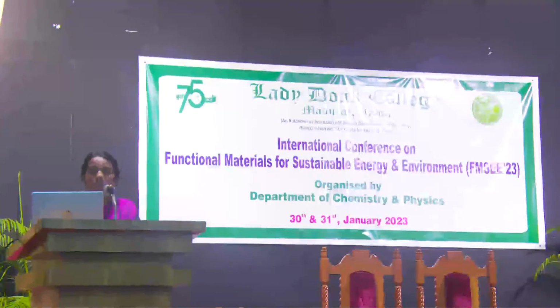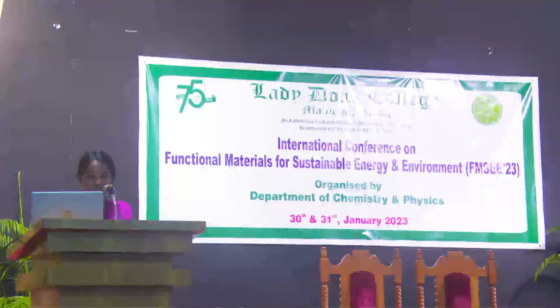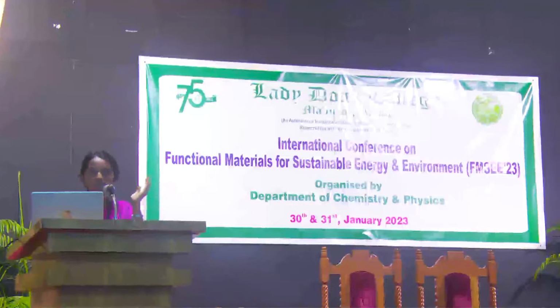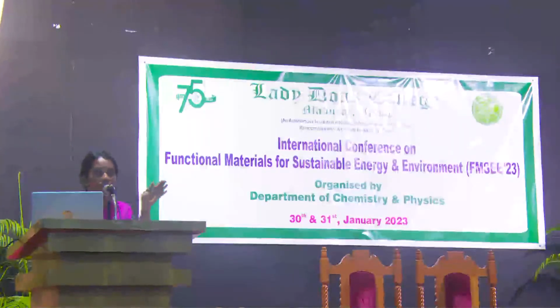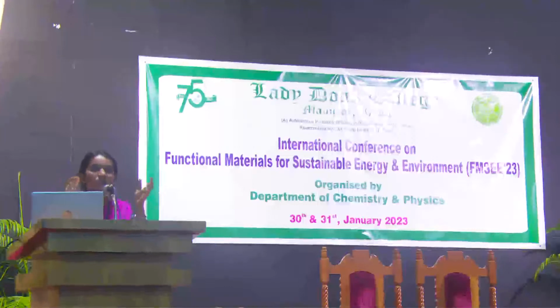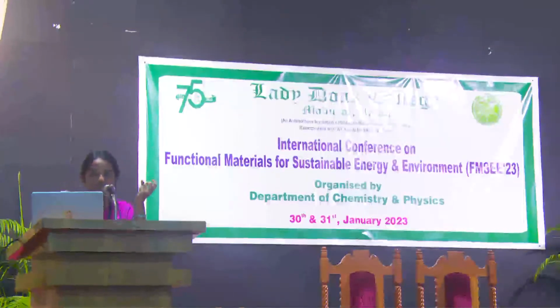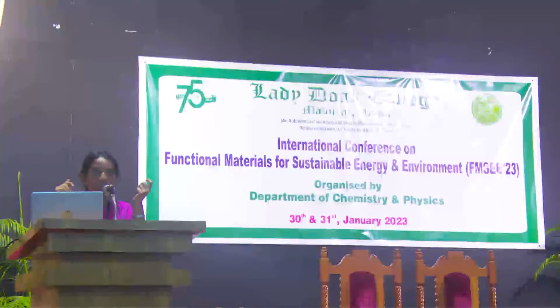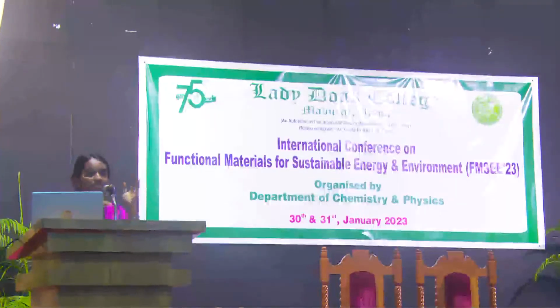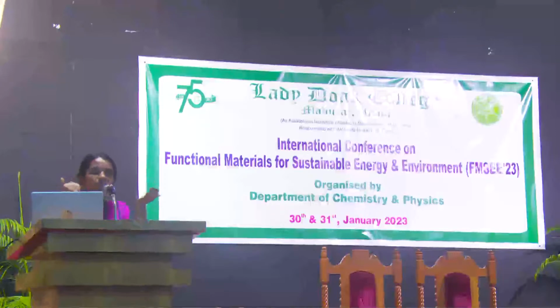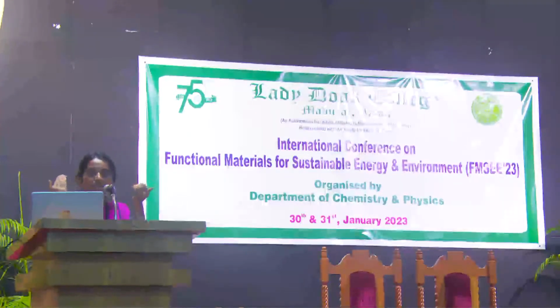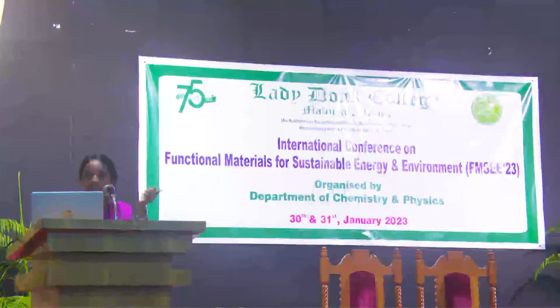Finally, we conclude that graphene oxide was successfully synthesized via modified Hummer's method. The structural characterization was analyzed via XRD and SEM analysis. The sheet-like morphology of graphene oxide increases fast ion transfer throughout the material. The electrochemical performance confirms the graphene oxide we prepared acts as a power source, obeying the capacitive charge storage mechanism, and the maximum specific capacitance was attained at 116.96 farad per gram at a 1 ampere per gram current density. Hence, these excellent properties suggest that the prepared graphene oxide may act as a better cathode medium for supercapacitor applications. These are my references.